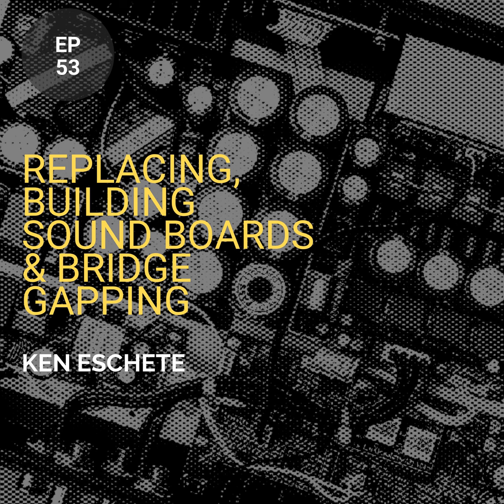So the next step was to do it on an action frame. Dale Irwin and I were talking on the phone. I told him I had this idea, and he sent me 2 Steinway action frames out of his trash bin. And this is an example, a close-up photograph of very, very badly stripped holes and cracks in the brass. And this is a photograph that I took after I'd filled the holes with this low viscosity epoxy. And you can see the epoxy is now traveling along the crack. It is now between the brass and the dowel. It's in the crack, and it's everywhere.